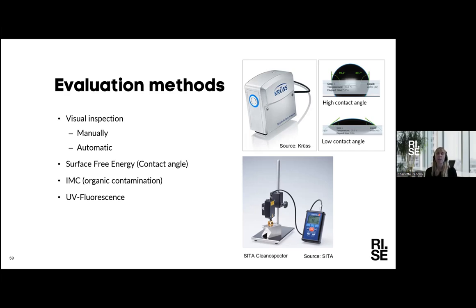Measurement-wise, we have some examples, there are more. For example, to measure the surface free energy of a surface, what you measure is the contact angle. You have a water and a non-polar liquid, and from that you can calculate the surface free energy. If you have a higher surface free energy, your water spreads out more easily on the surface, so you can see if you have cleaned away at least oil or other contaminants. But it can be difficult.